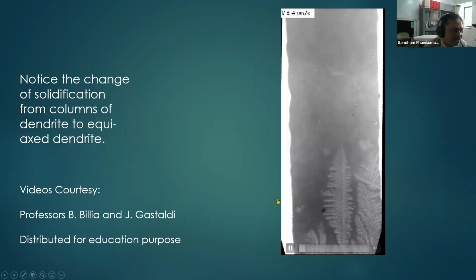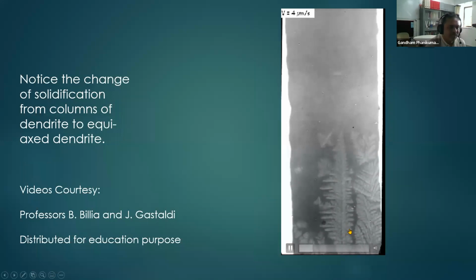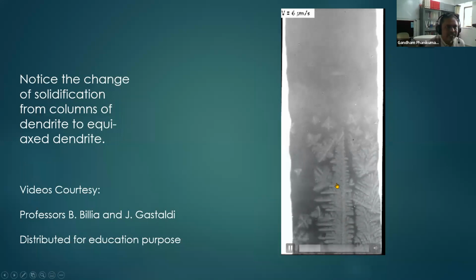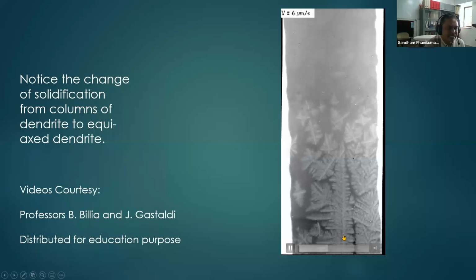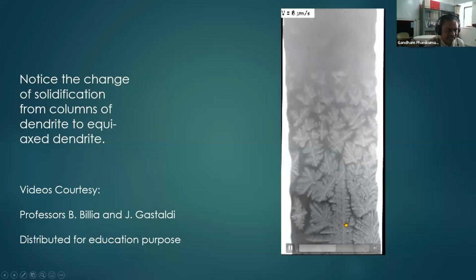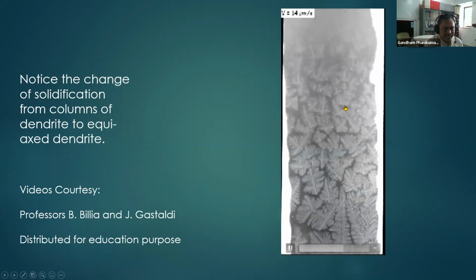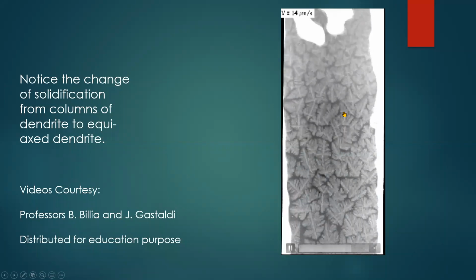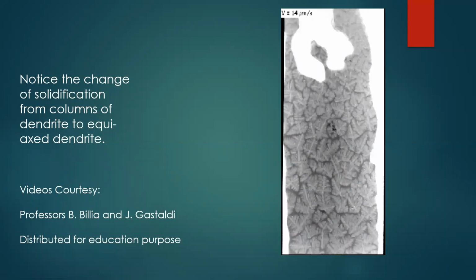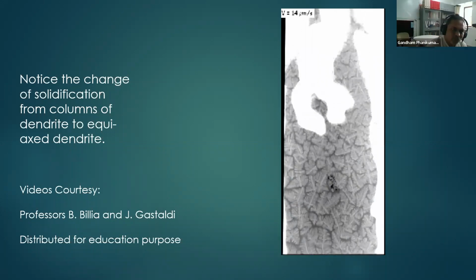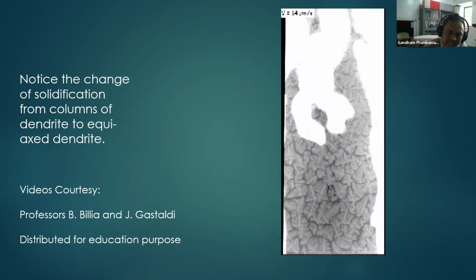Yeah. So what you are seeing, I will tell you. You are initially growing slowly, then you have increased the speed. So what happened is that initially it was growing as dendritic, but later on the equiaxed growth has taken over. So this transition is called the columnar to equiaxed transition. Okay, so this transition happens in ingots, it happens in welding, it happens in additive manufacturing also.